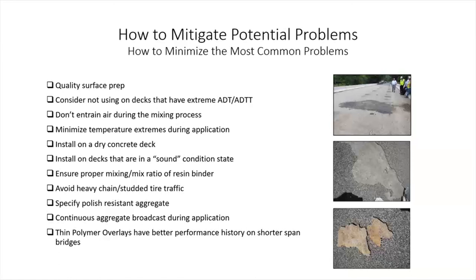We talked about aggregates and continuous broadcasting of the aggregates. We like to make sure there's a wet line of the resin, that you don't stop the resin in the aggregate. Keep going, because if you stop the aggregate and the resin starts to set up, when you start back up, you may have a little bald spot. And the other thing is, just historically on shorter spans, I look at some of these studies, they're seeing a little bit better long-term life cycle on shorter spans, but that doesn't mean on long spans you won't get really good long life cycle. It's kind of a combination of all these factors. That's why I'm mentioning all these factors.